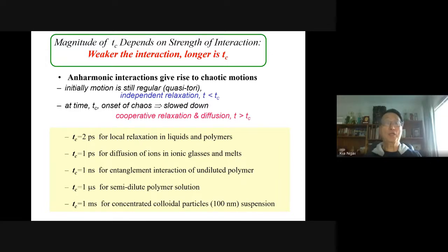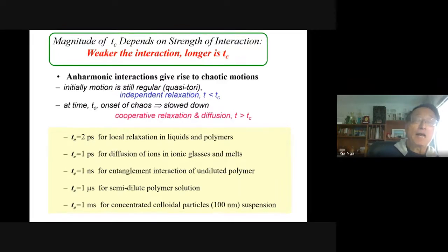Sure, yeah. I think I have a paper already, maybe 10 years ago, addressing this. Look at the cartoon already there. Let me give you an example, glycerol, that's the best example. It has a very small n, 0.3 or so, and so it has a narrow alpha relaxation, and the JG beta relaxation strength is very low compared with the alpha.